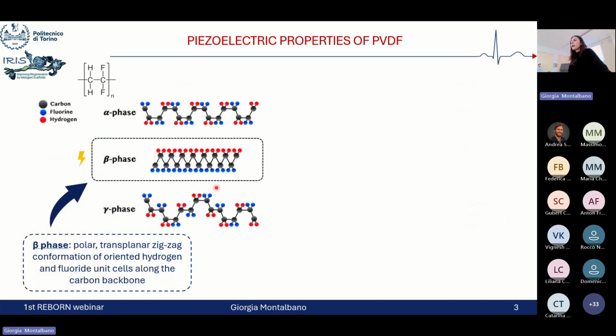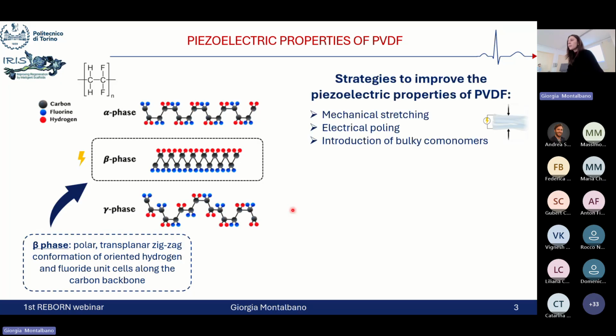Polyvinylidene fluoride is characterized by a semi-crystalline complex structure presenting 5 distinct crystalline phases, where the beta phase is the one responsible for the piezoelectricity of the material, due to its polar all-trans planar zigzag conformation of oriented hydrogen and fluoride units along the carbon backbone. So this means that by acting on the final content of the crystalline phase of this polymer, we can modulate the piezoelectric properties of the final substrate.